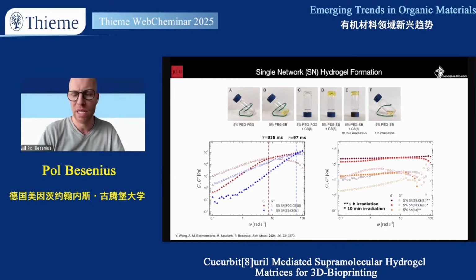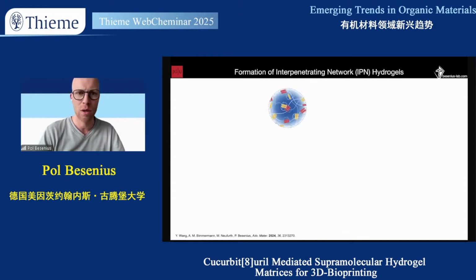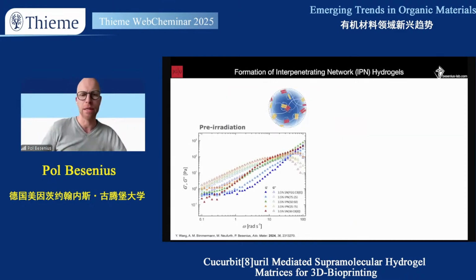the solution. Because if you look at the orange data points without CB8, you do get network formation, but the network is much weaker compared to the presence of the supramolecular crosslinker. Now, the neat thing is that you can mix, right? So you can mix FGG, so tripeptide-functionalized star PEGs, with stilbazolium-functionalized star PEGs.